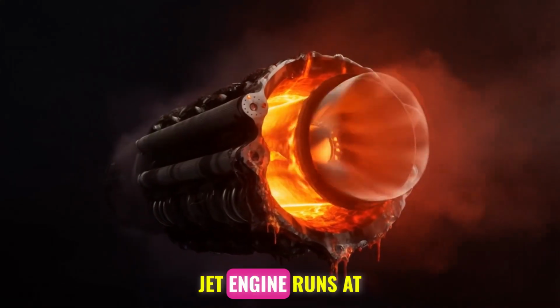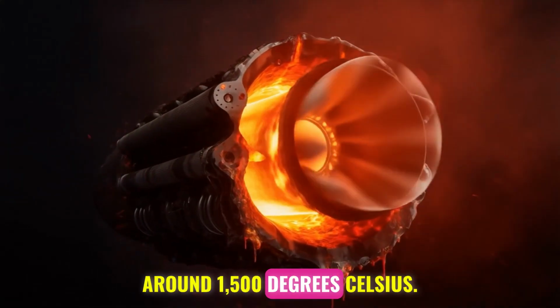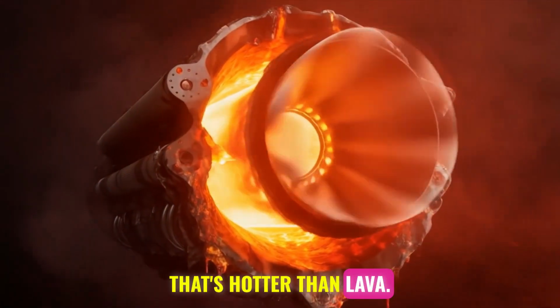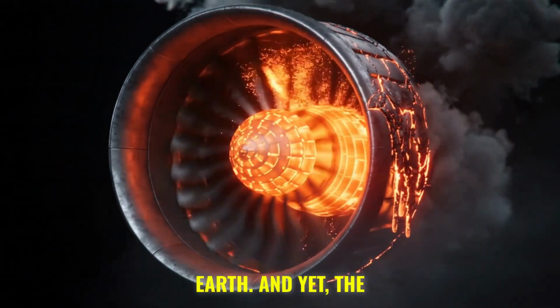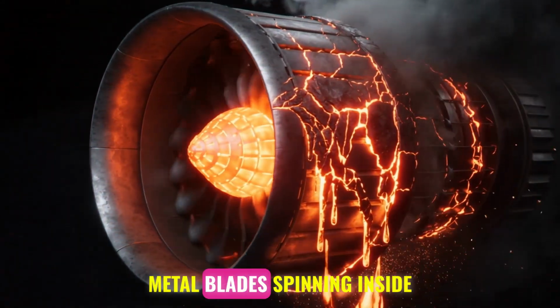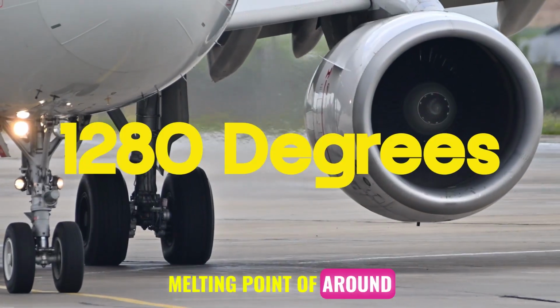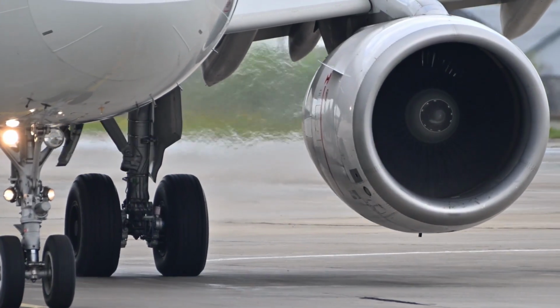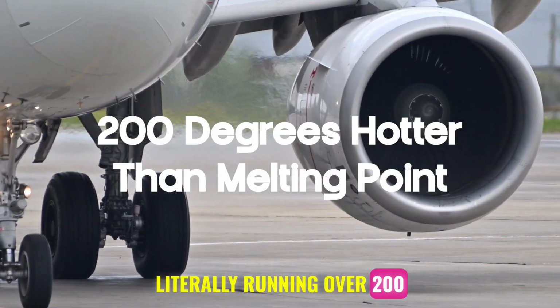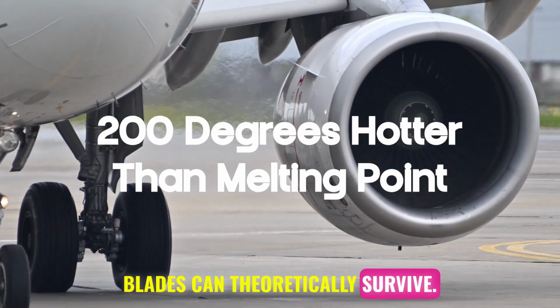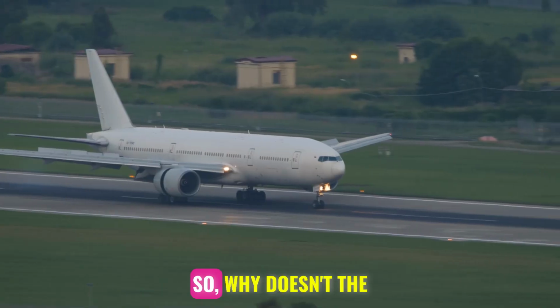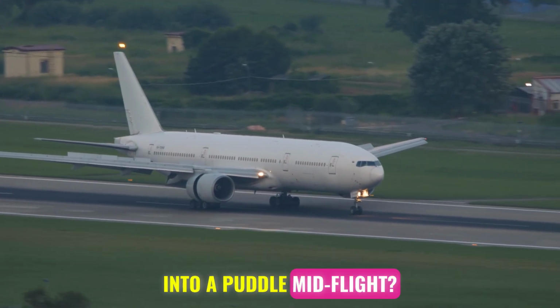The inside of a jet engine runs at around 1,500 degrees Celsius. That's hotter than lava. That's hot enough to melt most metals on Earth. And yet, the metal blades spinning inside that engine have a melting point of around 1,280 degrees, so the engine is literally running over 200 degrees hotter than the blades can theoretically survive. So, why doesn't the whole thing just turn into a puddle mid-flight?